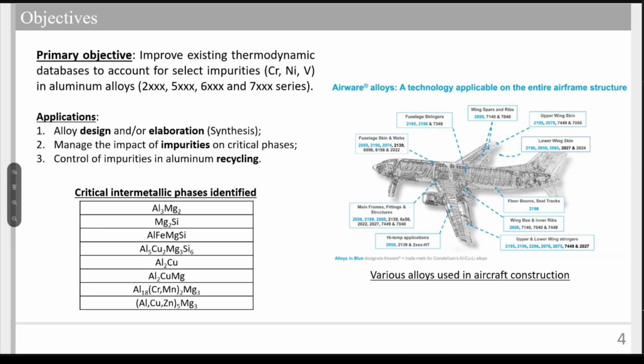My primary objective for my master's project is to improve the existing thermodynamic databases to account for select impurities, once again chromium, nickel, and vanadium, in select aluminum alloy series. Here we targeted the 2000, 5000, 6000, and 7000 series. These series are interesting because they are high performance alloys used in automotive and aircraft production. We have already identified some of the important phases that we want to look at, seen in this table here. As applications, we aim for improving alloy design and alloy elaboration, taking into account the impurities we mentioned. We want to help manage the impact of impurities on the critical phases, and perhaps most importantly in the current climate, the control of impurities in aluminum recycling.